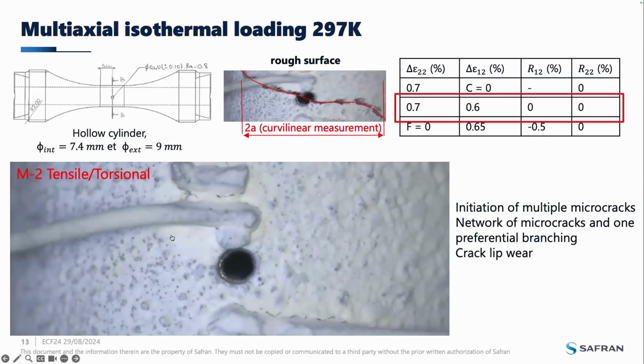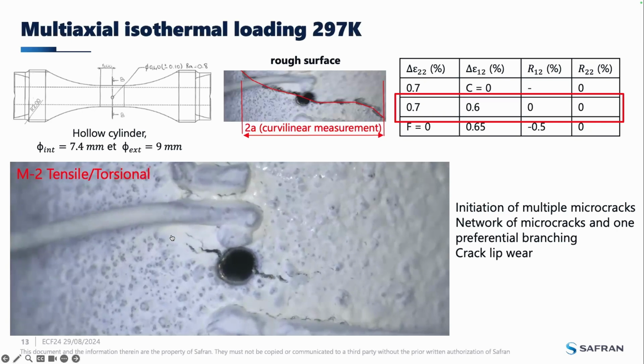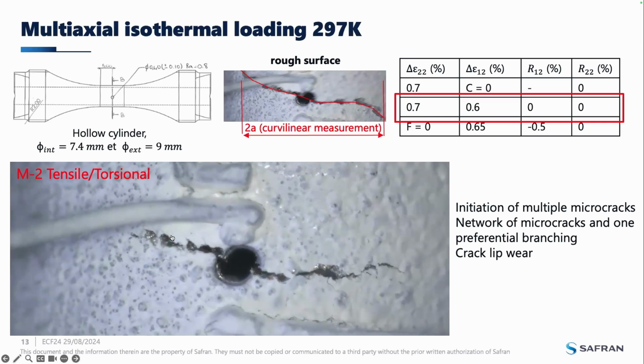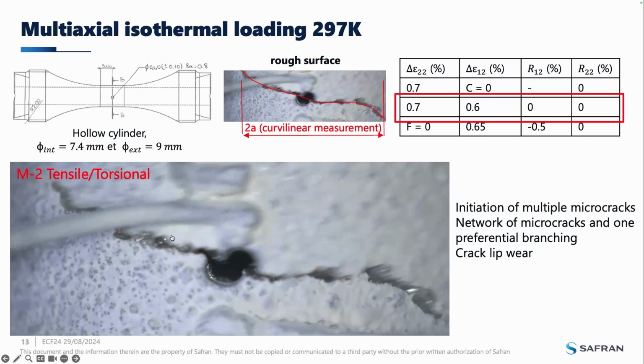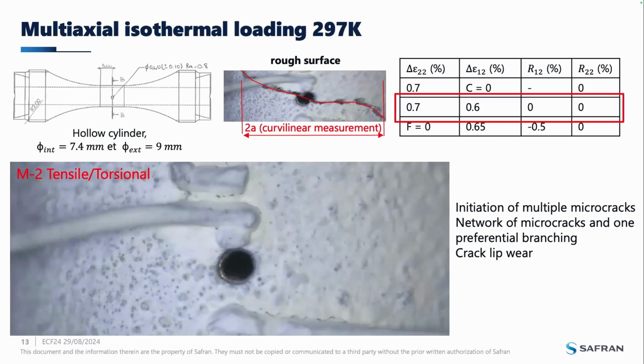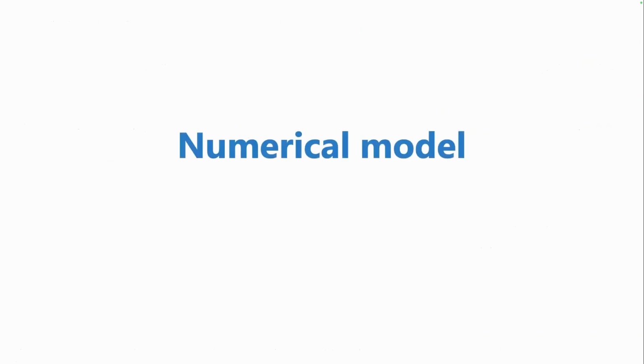So as you can see, there is initiation of multiple microcracks, and for each crack tip there are networks of microcracks, but only one preferential branch is growing, and you can also notice crack lip wear. So based on all this experimental result, I am going to present you the numerical model.